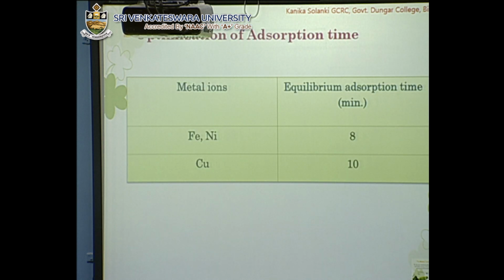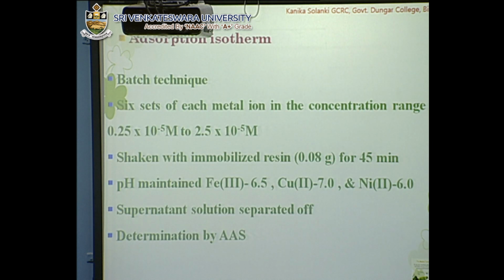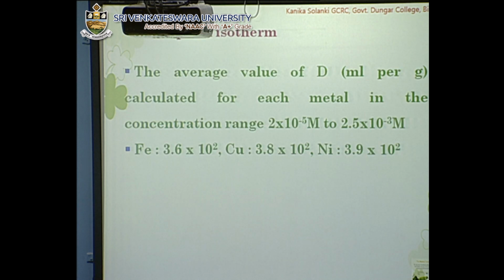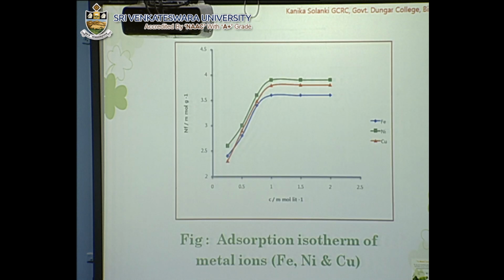As you can see in the table, the equilibrium adsorption time for ferrous and nickel is 8 minutes, and for copper it is 10 minutes. The adsorption isotherm, again the batch method is used, 6 sets have been prepared between the range of concentration, pH was maintained, and the supernatant solution was determined by the AAS. Absorption isotherm values are also given. Now this is the graphical representation of the adsorption isotherm of ferrous, nickel and copper.